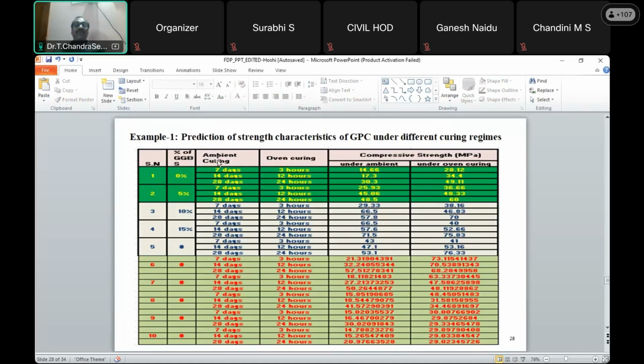But it's not suitable for winter and rainy seasons. This ambient curing is suitable only for the summer season, where temperatures are very high. Only in the presence of high temperatures will polymerization take place, and according to the polymerization, it will generate the strength. Gels will be formed. If the temperature falls below that, the gel will not form, and it will not bind any material. So that is ambient curing.